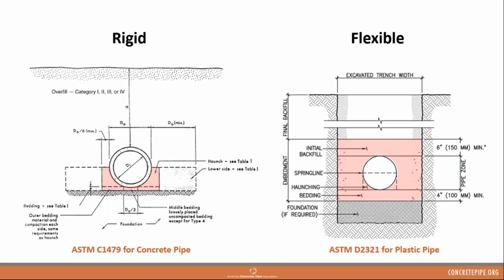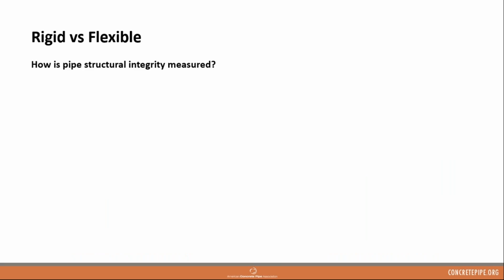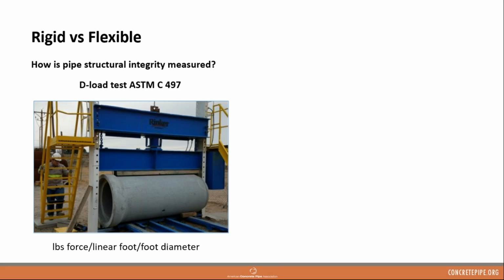So another logical question after learning about the structural importance of buried infrastructure is, how is pipe structural integrity measured? Well, for reinforced concrete pipe, we have a test called the D-load test. This test loads the pipe via a hydraulic beam, and we're definitely wanting to capture two critical points. The first one is where this pipe will develop a 0.01 inch crack, and the second one is loading it to ultimate. So the load is measured at each of these points and then recorded.